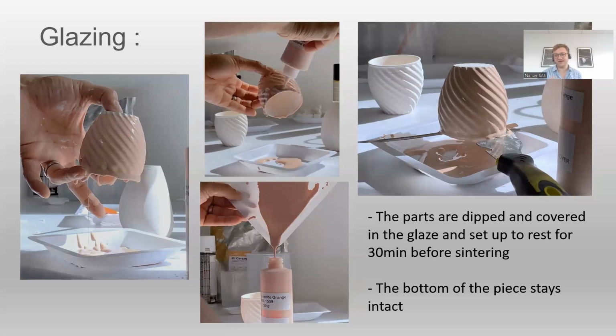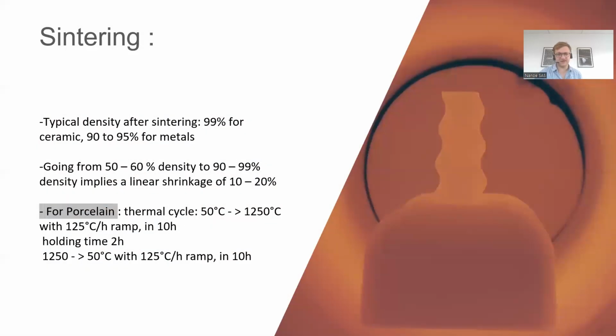And then you'll put that part back in the furnace a second time, heat it very quickly to 1,200 degrees Celsius. This second sintering is much quicker than the first one. And in that stage, the particles of glazing will actually melt and fuse with the surface of your part. So sintering is a process that our customers already know very well, of course. It always implies densification of the part, and that means a shrinkage, always in the same range, something like 15 to 20%.